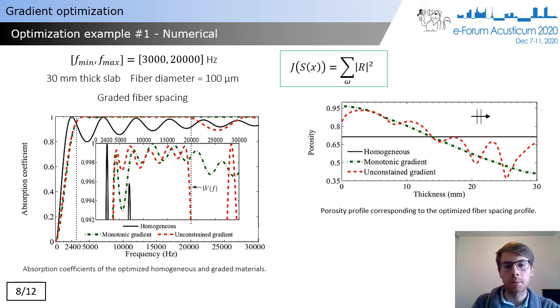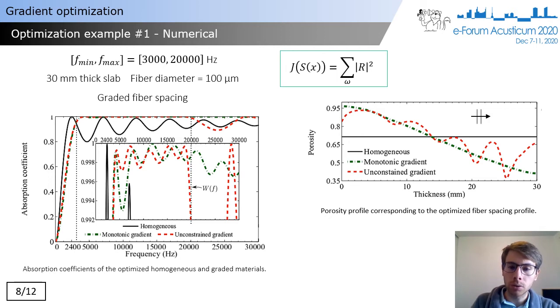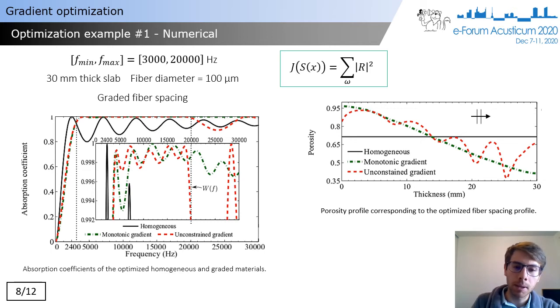The red profile has been optimized by our method. The corresponding porosity profile shows a global decrease of porosity, but with five oscillations added to this decreasing profile. These five oscillations allow us to tune five modes of the porous layer. You can see in the absorption coefficient that there are now five absorption maxima in the frequency range of interest, meaning the absorption maxima have been redistributed and forced into the targeted frequency range.